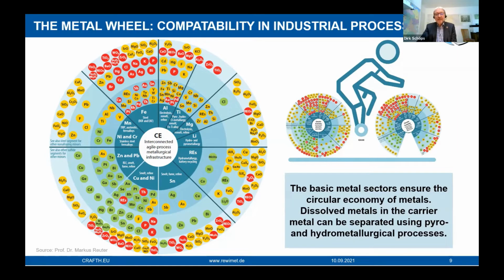And the same is already developed for the treatment of batteries, lithium batteries. When you bring them into the copper process, like here, you can easily obtain copper and nickel and cobalt. Cobalt is here, nickel is here, there's no problem. The problem is the lithium. Lithium is not marked here, but if you melt only the batteries and do not mix this with other copper scraps in a large smelting oven, then you can obtain a slag from which you can recover the lithium. This is possible.